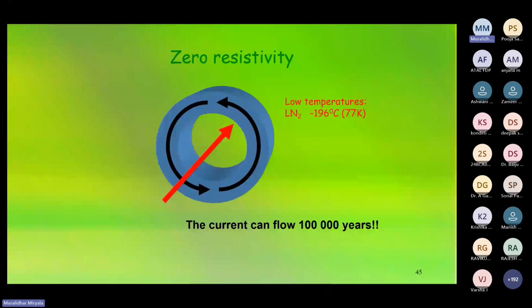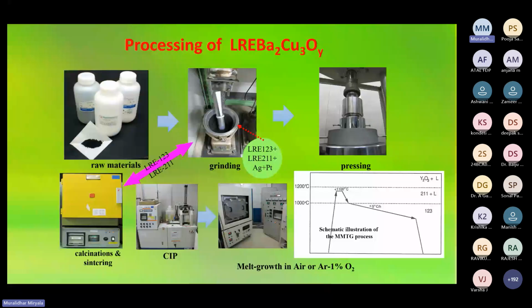So these materials can be made using the melt growth processing technique. What we developed is the modified melt growth. What I show in the figure on the bottom right is the processing condition of the modified melt growth technique. Here, very important is the LRE Ba2Cu3O, the 1:2:3.